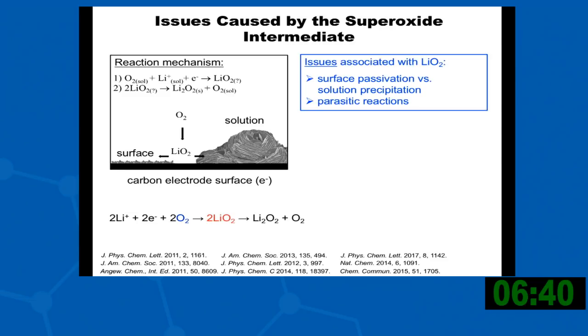So just to reflect a little bit on some of the problems of the superoxide intermediates, one of the main mechanisms is that you react the lithium with the oxygen to form the lithium superoxide, which then disproportionates. Now remember, this reaction is mediated by electrons coming from the electrode structures, and because of that, the peroxide ions, which are largely insoluble in most electrolytes, precipitate out, disproportionate, and you very rapidly form these surfaces that are passivated by lithium peroxide, which is an insulator. And so you prevent the reaction from going on. And so you also, again, get these parasitic reactions because of the highly aggressive nature of the superoxide.